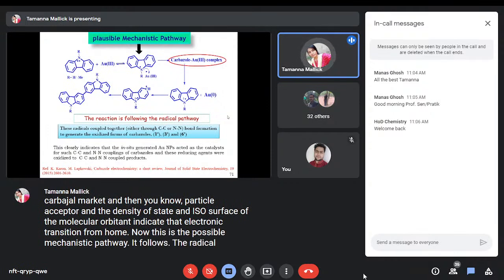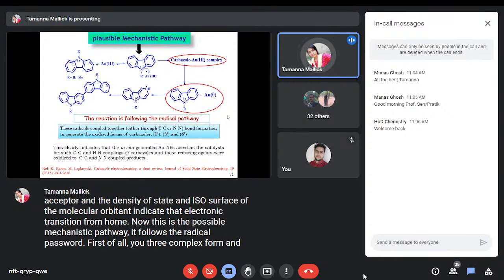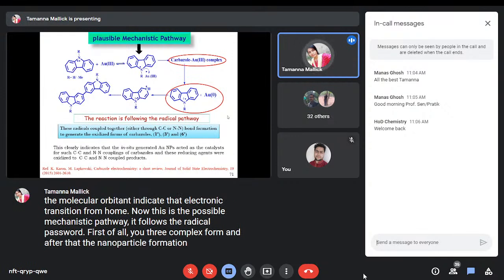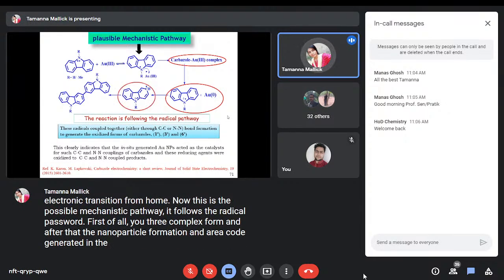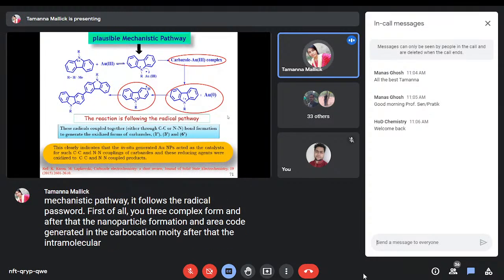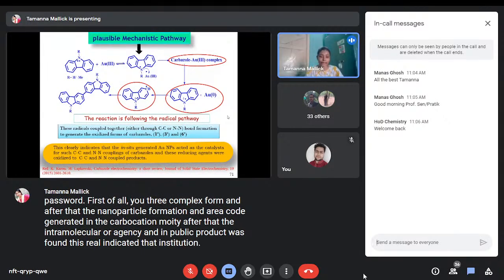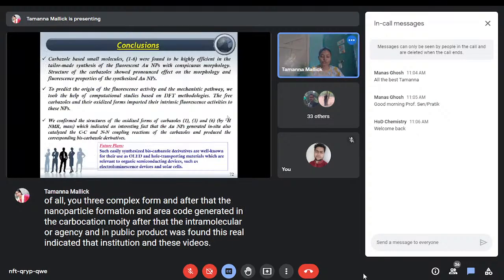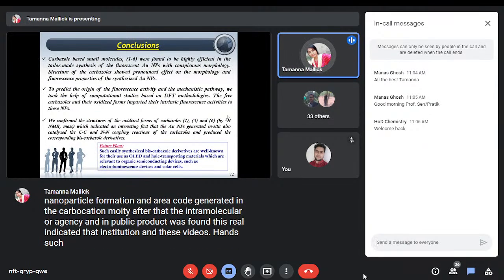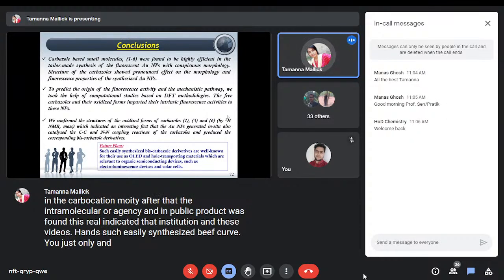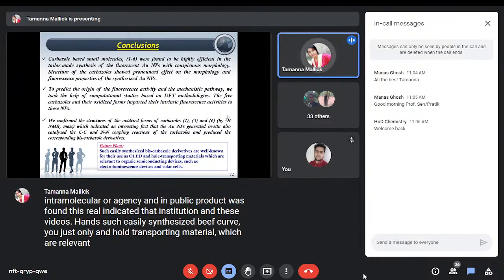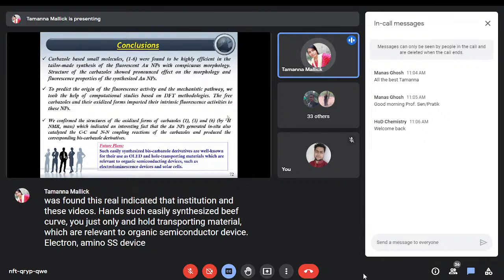It follows the radical pathway. First of all, the carbazole Au3+ complex forms, and after that nanoparticle formation occurs, and a radical is generated in the carbazole moiety. After that, the intramolecular C-C and N-N coupled product is formed. This clearly indicates that the in situ generated gold nanoparticle acted as a catalyst for such C-C and N-N coupling, and the reducing agent was oxidized to the C-C and N-N coupled product. Hence, such easily synthesized bis-carbazole derivatives are well known for their use as OLED and hole transporting material, which are relevant to organic semiconductor devices such as electroluminescence devices and solar cells.